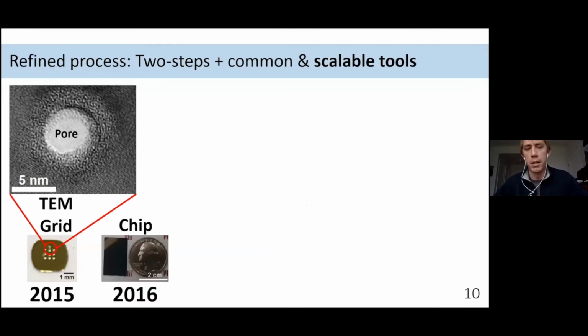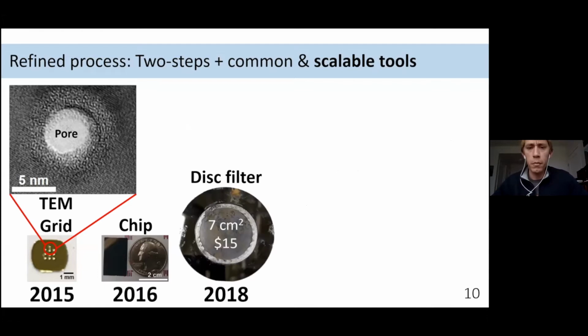and then started to scale this up to something that could actually look like a membrane product in the near future. So we went to the chip scale in 2016, and then moved to our first functional membrane type of morphology in these disc filters. For those of you who are in the microelectronics space, you'll recognize this as a silicon wafer that's been treated to be initially thinned and then chemically etched through using the process that we developed.